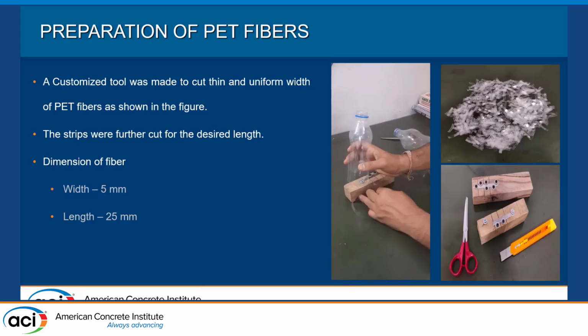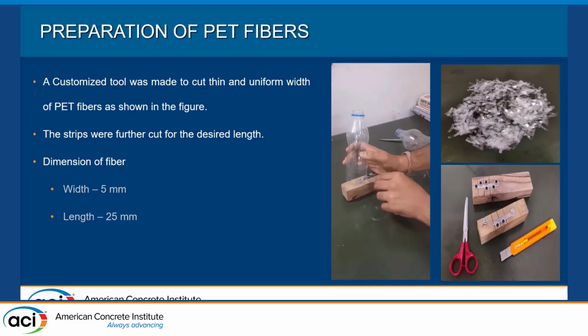The major challenge with this plastic was getting the aspect ratio, because the aspect ratio plays a very important role in the bonding of the concrete when we get the final results. So the width decided was 5 mm and the length was 25 mm. And we got the fibers you can see on your right.